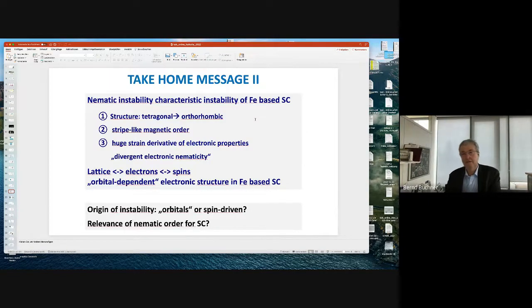And that's already the take-home message too, that we have this nematic instability as a characteristic feature of these iron-based superconductors. We have these three things: structure, magnetism, we have orbitals. And this means, I believe, that we have really an orbital-dependent electronic structure in these iron-based superconductors. And still, we have this question: what is the driving force? And the second question, of course, is it in some sense relevant for superconductivity? Can we find evidence for that?